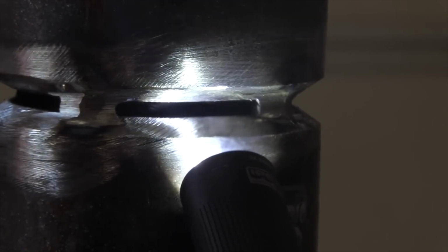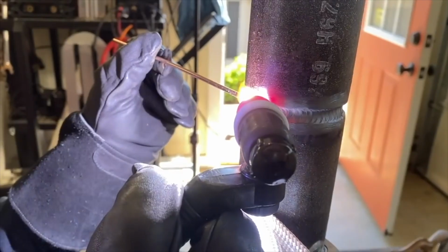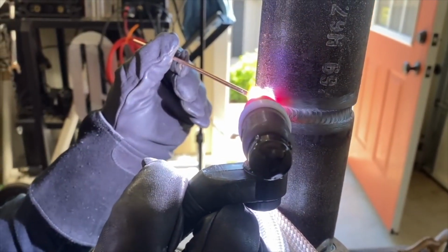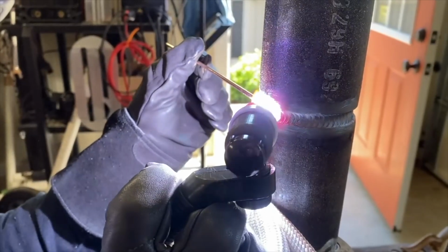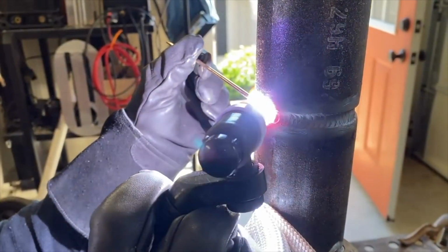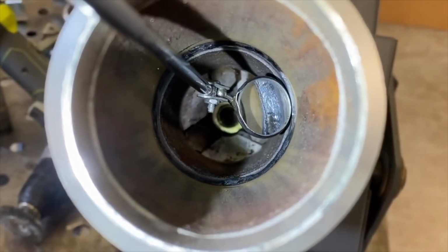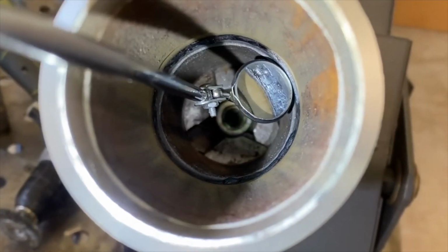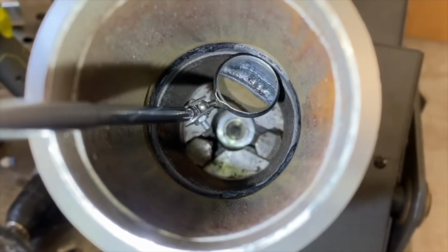In addition to that 6G you saw earlier, I worked with Andrew on this 2G, 1/8 inch gap, 1/8 inch filler wire, TIG all the way. 100 amps was pretty good for a lay wire root. Bumped it up just a little bit for the hot pass. This joint was freehand all the way out, which would probably be the common technique for a boilermaker to use because they don't ever have room to walk the cup. The video shows all the passes all the way out to the cover pass. This is just the root and hot pass.